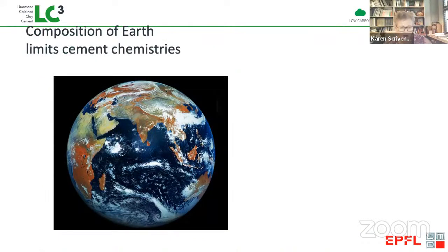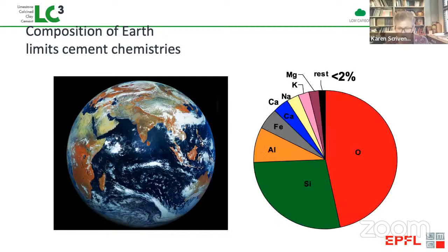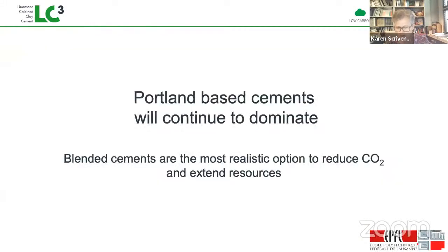Now, we're ultimately limited by the composition of the earth. Just 8 elements make up more than 98%. That's oxygen, silicon, aluminium, iron, calcium, sodium, magnesium, potassium. And because of this, we really are limited to producing Portland cement, because Portland cement is based on very abundant raw materials and can be produced in the quantities we require.